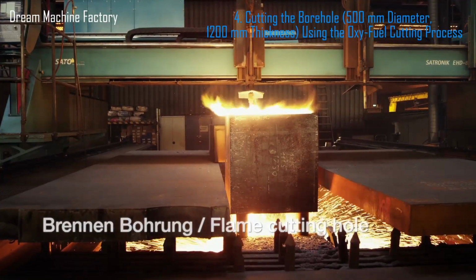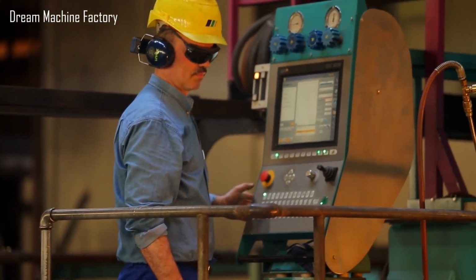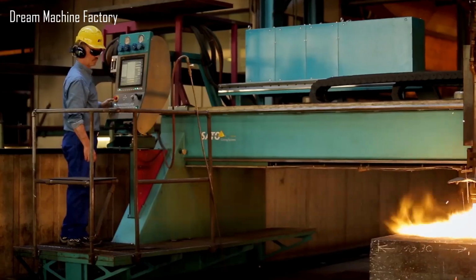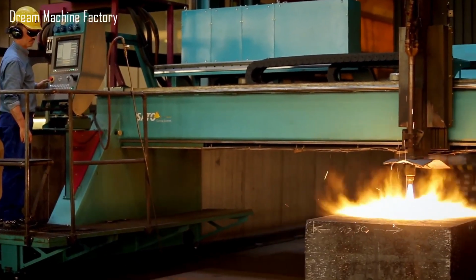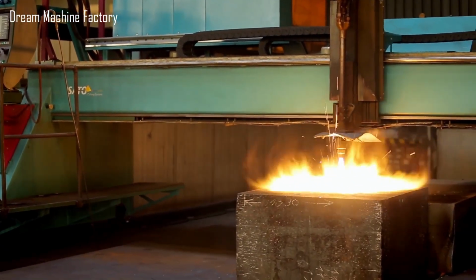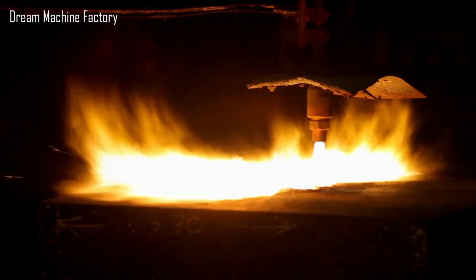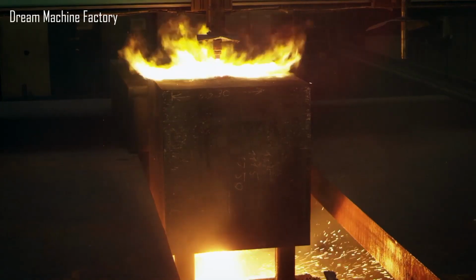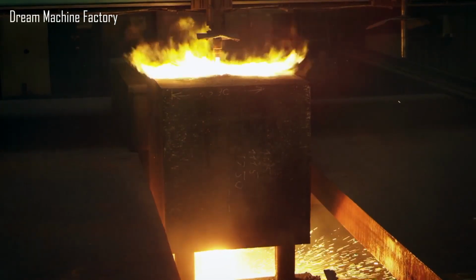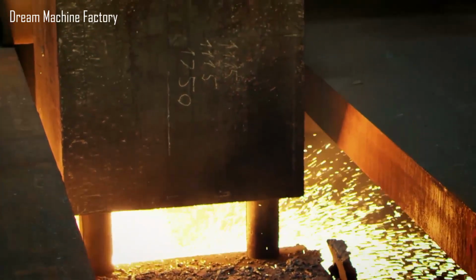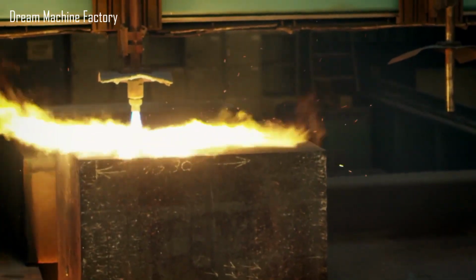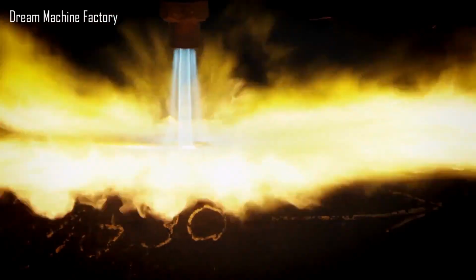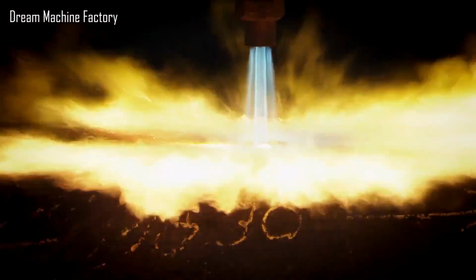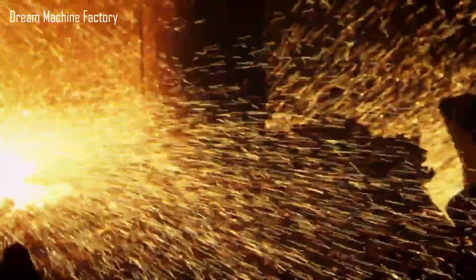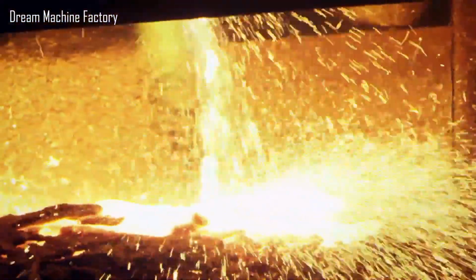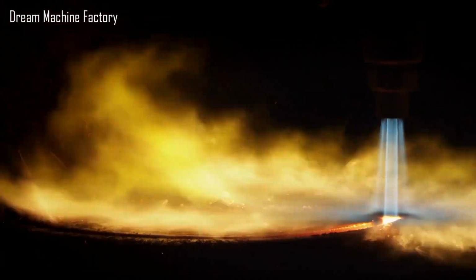After piercing the initial hole, the full borehole was cut using the oxy-fuel cutting process. A specialized cutting torch delivered a precise mixture of fuel gas and pure oxygen to generate a high-temperature flame, which heated the steel to its ignition point. Once the steel began to melt, a focused jet of oxygen oxidized and blew away the molten material, allowing for a clean, controlled cut. The result was a cylindrical borehole 500 millimeters in diameter and 1,200 millimeters deep, showcasing the precision of thermal cutting.